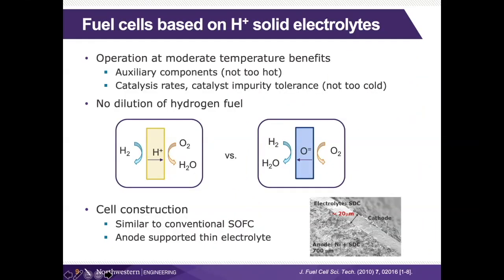Now, I described to you also this oxygen ion conductor for electrolysis. Well, let me tell you some differences between operating a fuel cell using a proton conductor versus using an oxygen ion conductor. One of the key issues is that in fuel cell mode, once you provide the hydrogen, it moves across the electrolyte, the product water is produced on the air electrode side. And so there's no dilution of this hydrogen as you run the process.